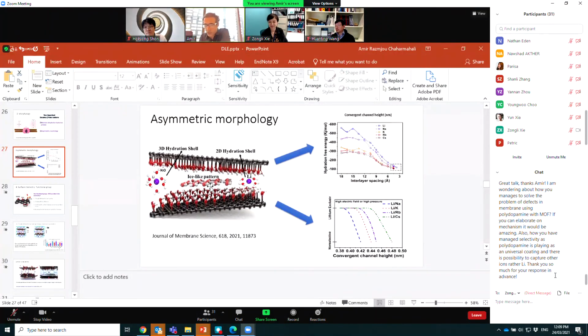Thanks. That's a great question, Parisa. I guess you asked a couple of questions at the same time, so let's go through them one by one. The first one is defects. Defects are a big deal for us, particularly for MOFs. Currently the way we address defects is we try to increase the thickness and also create multi-layers to reduce the defects. And after we create the MOF thin film, we try to fill the pores, the defects, with inert materials and create sort of charge exclusive barriers inside the defects. It's not the best solution, but it's something that we are currently working on.